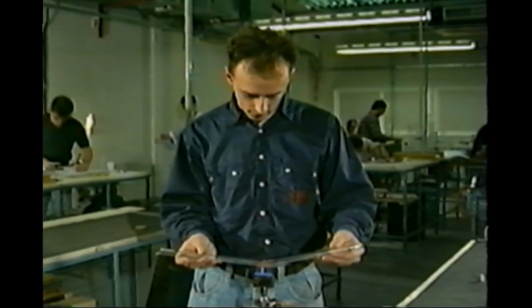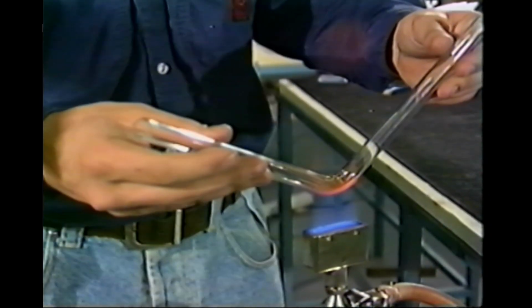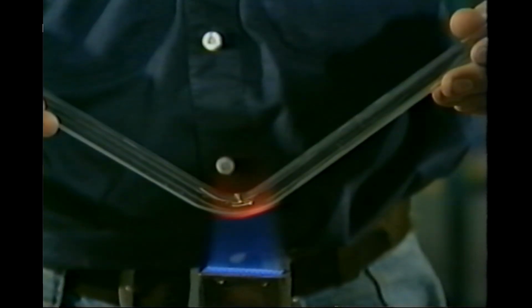Keep the tube in the flame and give the area opposite the mark, this will be the outside radius of the bend, additional melting. To aid formation of this bend and make the tube movement easier, as the outside of the bend is undergoing the extra melt, raise both ends of the tube each to an angle of approximately 45 degrees, at the same time ensuring that the radius on the melted area of glass is rounded and equal either side of the pencil mark, and the mark is centrally situated in the radius. It's essential that this is a radius shape and not a V shape.